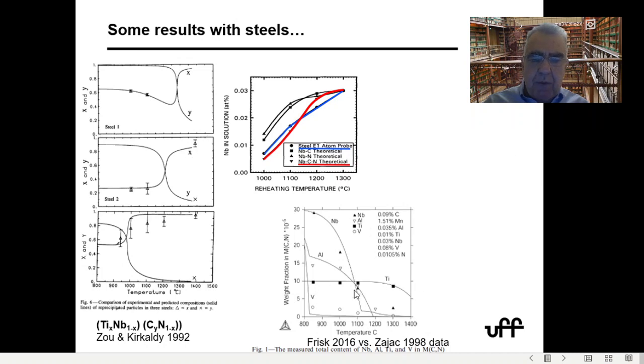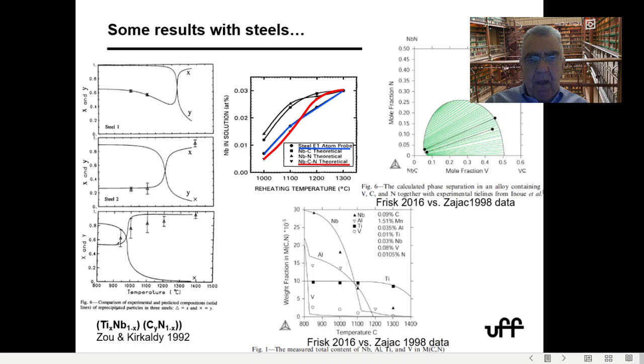Later on, with the assessment by Karin Frisk, we see very good agreement of the compositions, and the assessments from there on were able to describe very well the miscibility gap, for instance, here between niobium carbide, vanadium carbide, vanadium nitride, and niobium nitride. So this is the region where you have immiscibility at around 1000 or 1200 C, and these are values measured with TEM, so it's a real challenge to do this experimental measurement, but you can see the modeling works very well.